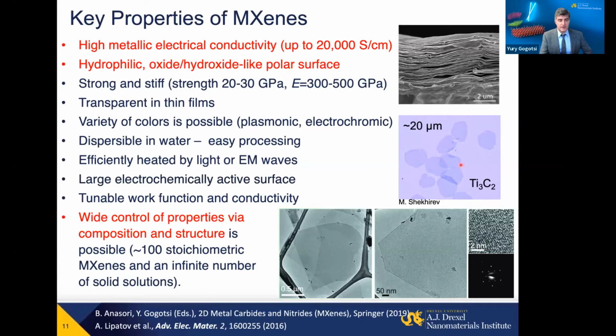So it's about 20 micron flakes in an optical micrograph of titanium carbide MXene. These flakes can be assembled into films. If you look at a single flake at high magnification, you will see that those are single crystal particles. Electron diffraction shows their crystalline nature. You can see some of them inherit this hexagonal shape from a precursor ceramic material. You can also see it in optical images here, but they are conductive. They are water soluble. They also are mechanically strong.